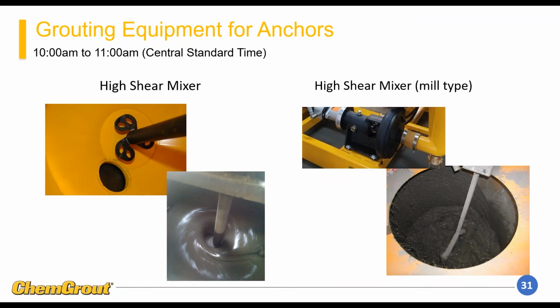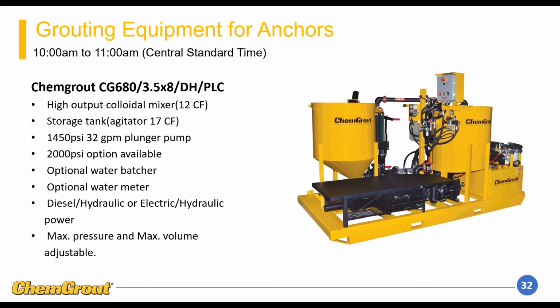We have a couple different types of mixing systems we offer for making colloidal grout. When you're doing hollow bar anchors, you need to have a high shear colloidal type mixer so that you have adequate wetting out of each individual cement particle. There's two ways that we achieve that. One is with what we call a shear disc, which is a high-speed disc rotating at about 3,000 RPMs in the bottom of the mixing tank, and it shears up all the different cement particles. And then we also offer colloidal shear mill pumps, which is a centrifugal style close tolerance pump that offers a high shear into the material. Both of them will achieve a colloidal mixed grout. The shear disc takes a little bit longer than the colloidal mixed pump, which is much more efficient.